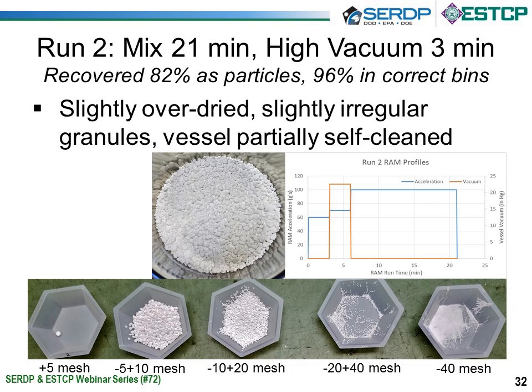So for run two, we reduced the total mix to 21 minutes by reducing the vacuum duration to 3 minutes. Again, we had that initial 3 minute 60 G no vacuum wetting period. Now we had 3 minutes of full vacuum at 70 Gs. After that 3 minutes, we again upped the G-force to 100 Gs for the rounding and the polishing. Here we saw that we were getting less of the overdried material. It was slightly overdried, and it was slightly irregular granules, but the vessel was becoming partially self-cleaned. We were getting a greater recovery percent. Here we recovered 82% as particles, and 96% of them were in the correct bins. So we were trending in the right direction.